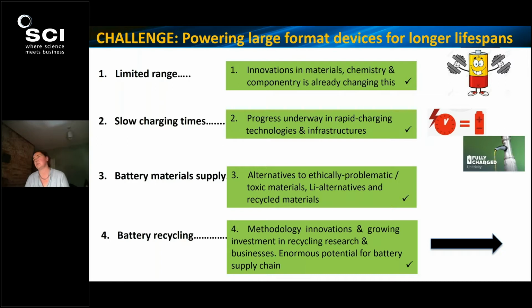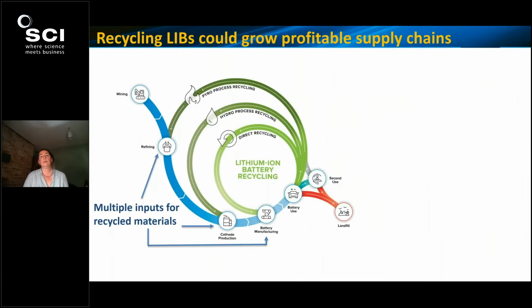And so there's an enormous potential for battery supply chains to capitalize on this, as we can see here. The recycling of lithium-ion batteries could prove very profitable for the UK. The blue line you can see is the route through battery manufacturing, from the mining of the initial materials, the refining of them to make them usable, both in purity, content, size and morphology, and then all the way through to the electrode manufacturing, the actual battery use, and potential second use considerations going forward.